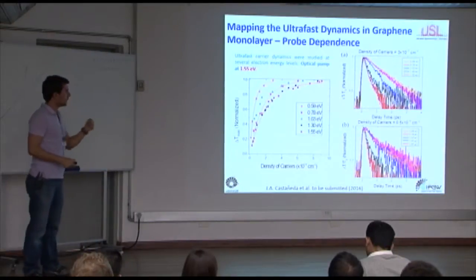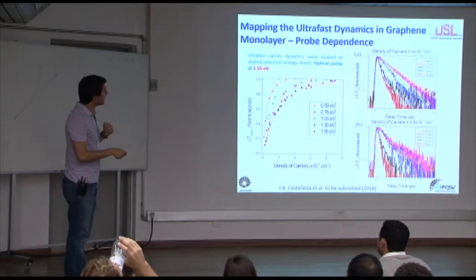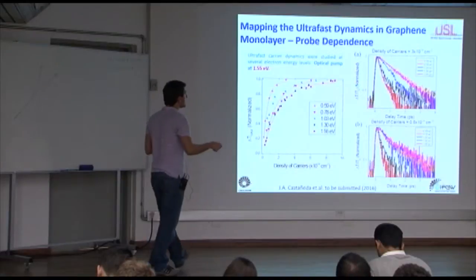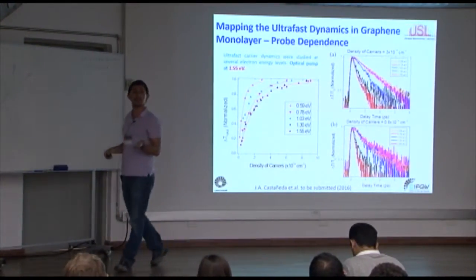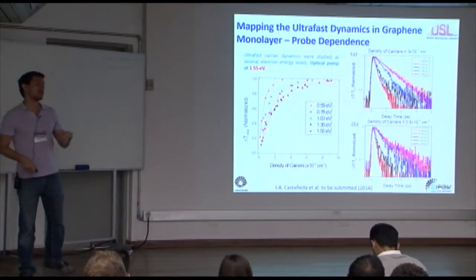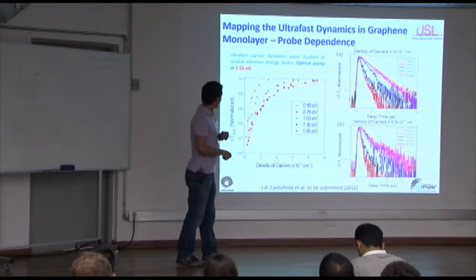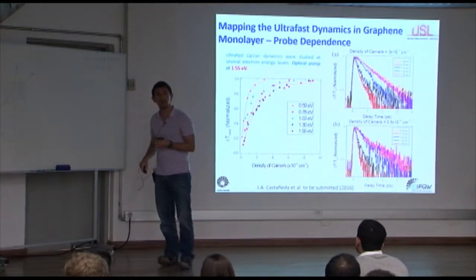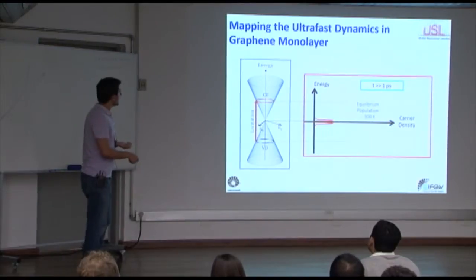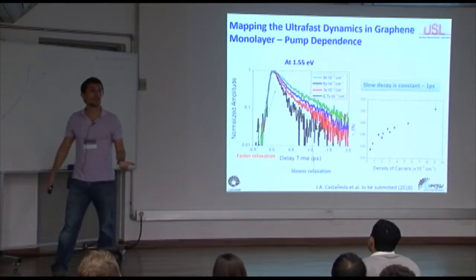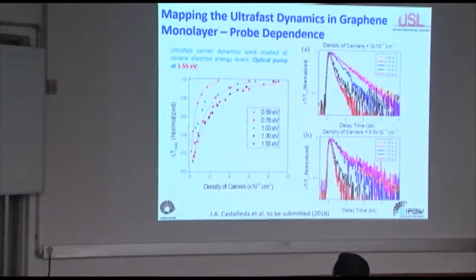So we're basically doing ultrafast spectroscopy on all those colors, just like for the quantum dots. Even for graphene, we can now see the electron cloud doing those movements and finally decaying. Unfortunately we can't go below about 0.5 eV — below the pump photon energy we couldn't recombine anymore, and we'd expect it to be very flat. Also, saturation occurs much faster at lower photon energies, which makes sense: less energy means you have fewer available states, so you saturate faster.